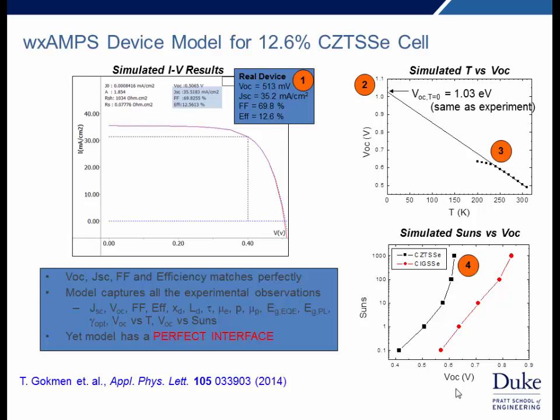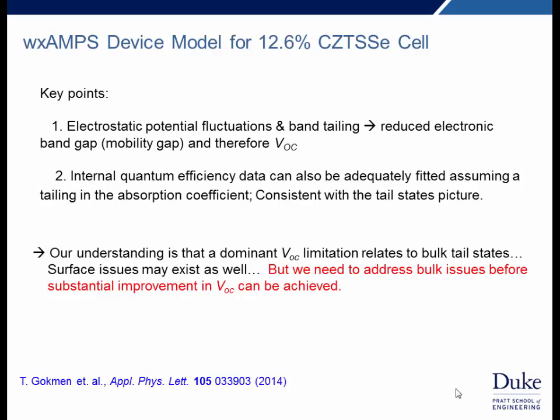And this can be incorporated into a device model. So in this device model, we can completely account for open circuit voltage, short circuit current, fill factor, efficiency, as well as a host of other measurements that we've made, including the depletion width and diffusion length, lifetimes, mobilities, band gaps, our VOC versus temperature results, which I showed you. But the important point is that we're not introducing any problem at the interface in this device. So device interface recombination is not necessary for explaining these parameters.